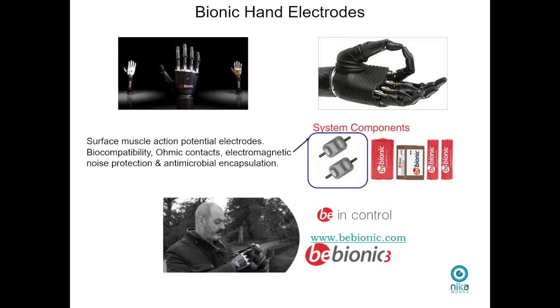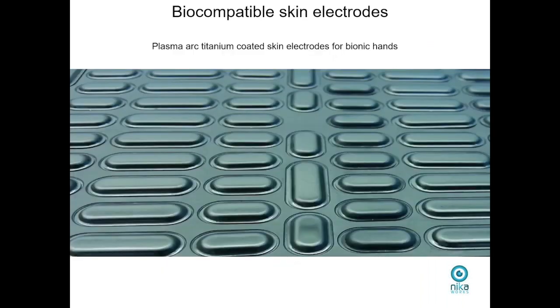Another thing at Nika Works, we work with a company called Bionic, who manufacture bionic hands in the UK, which are controlled by surface potential voltages picked up in the skin in the order of microvolts. So we work with these guys to make their surface skin contacts biocompatible. Presently they're made with stainless steel. Stainless steel can comprise many different elements, including chromium and nickel, which can irritate the skin. So we take these contacts and we coat one side with gold, real gold, because we're looking for an extremely good ohmic contact for the skin signal. The other side, which you can see in this image, is the skin side of the electrode, which is coated with a titanium alloy. Again, very thin, about 500 nanometers, ultra hard, biocompatible.